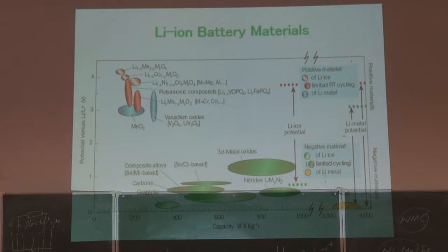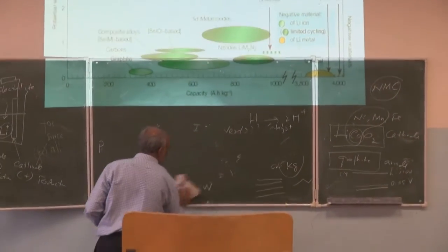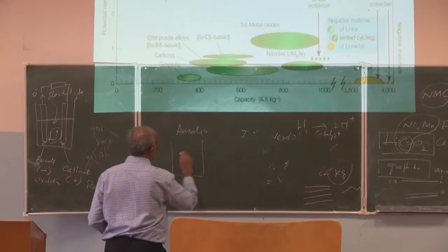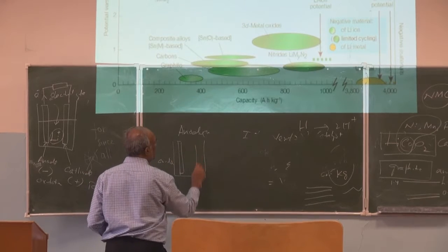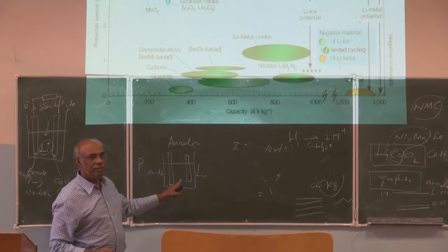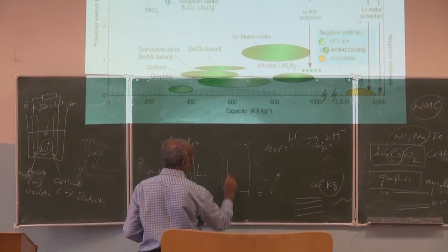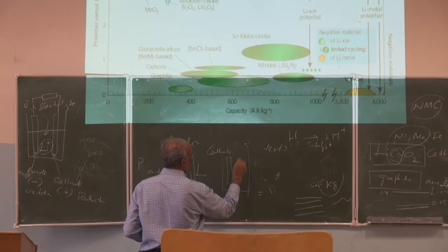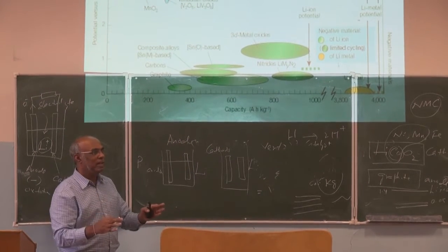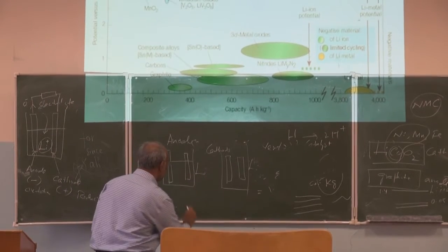one of the electrodes. It's not safe at all, right? But that's why when you study some anode material, what you do is you first test it with lithium. This is very important for anybody working in the battery area. Suppose I want to use some anode, you have to use that anode with lithium foil. So this is called a half cell. If you want to use a cathode, you always study your cathode with lithium. Right? Now, if you want to use the full cell, you have to use this one and this one. Right? That's how you make your real battery.